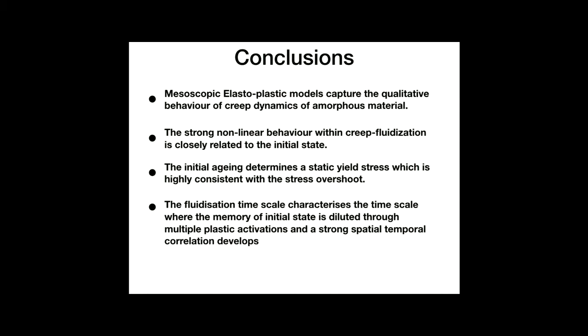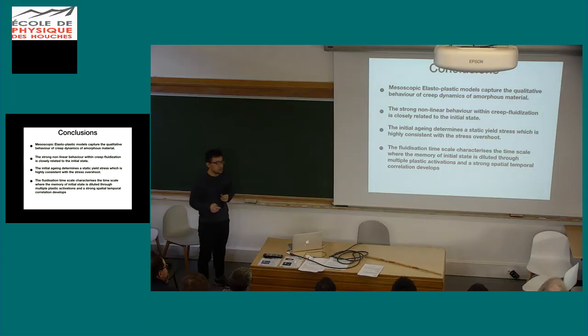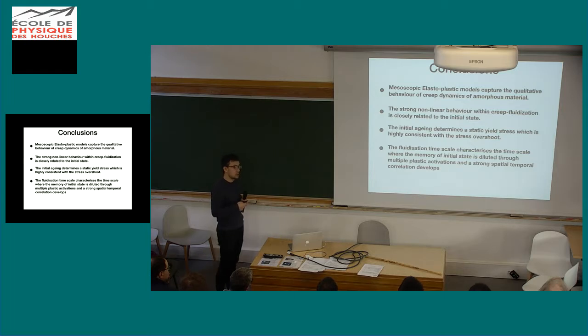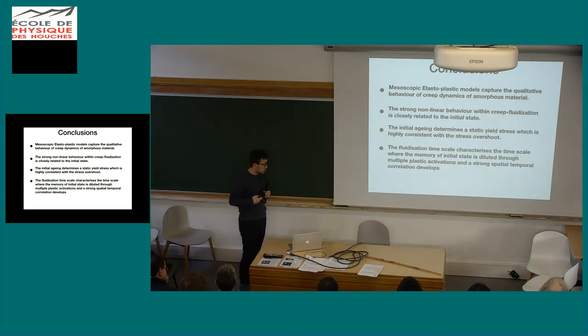To conclude, we have a model that is phenomenological and simple, but enough to reproduce the qualitative behavior in the creep. We can associate the fluidization time scale, characterized by the inflection point of the shear rate, with two physical meanings: the time scale beyond which the initial state is lost, and also where there is a strong correlation. And then we estimate the static yield stress, which is highly consistent with the shear stress overshoot in the quasi-static limit. And with that, thank you for your attention.